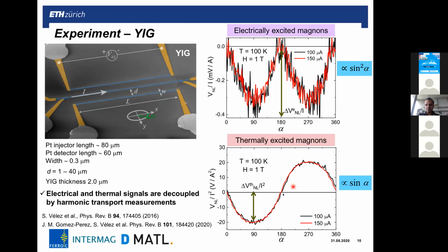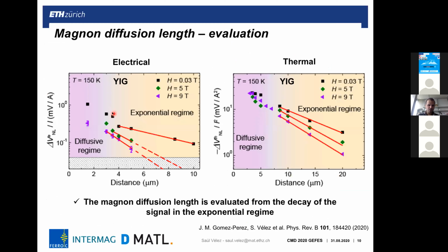So when we measure the second harmonic, we can detect the thermal magnons, and this leads to a sine phi dependence, because only the inverse spin Hall effect of the detector is involved in the detection process. So now I'm measuring this signal as a function of different distance. You can track the magnon transport, and you can extract the diffusion length of the magnon conduction in the system. Here I'm showing a particular case of 150 Kelvin. Comparing electrical and thermal magnon excitation, and by measuring the decay length in the exponential regime, we can extract the magnon diffusion length.